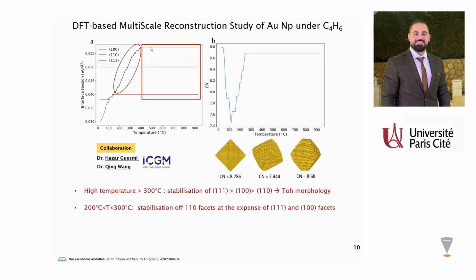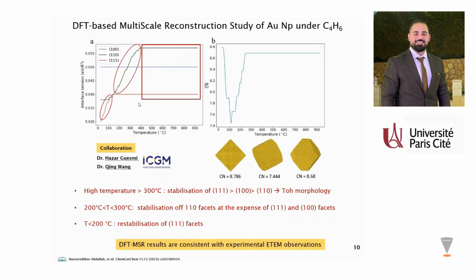Then, when we decrease the temperature between 300 and 200 degrees Celsius, we saw a stabilization of 110 facets at the expense of 100 and 111 facets, which can also explain the rounded morphology obtained at 300 degrees Celsius during ETEM observation. Finally, when we decrease again the temperature between 200 degrees and room temperature, we saw again a stabilization of 111 facets at the expense of the two other facets, which can finally confirm the growth of 111 facets obtained experimentally. So this DFT-based MSR study is totally consistent with our experimental observation.